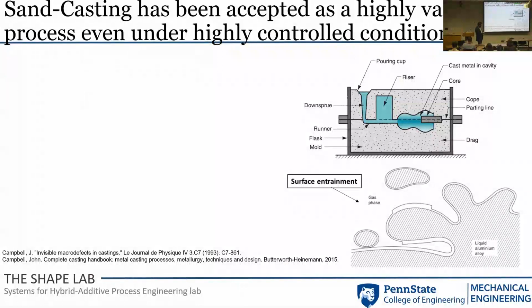So the liquid metal that first comes down the pouring basin into your sprue, and that first touches the sand, should get oxidized and will get oxidized. And ideally, you want it to be like your skating pipe. It stays like this nice pipe with a shell, and your clean metal flows through and fills your cavity.